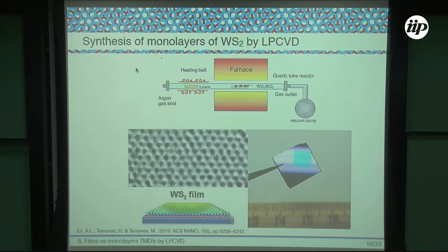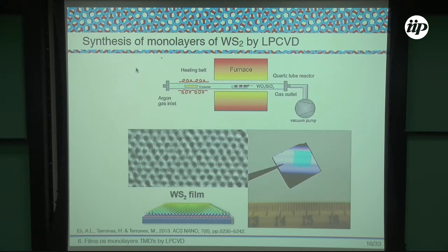This is another type of synthesis — how to synthesize films of TMDs. For some applications, it is better to have large areas of TMDs. To grow these samples, you use low-pressure CVD by adding a vacuum pump at the outlet of the quartz tube to decrease the pressure inside. This gives films of nearly 1×1 cm on silicon. So by changing parameters in the synthesis setup, you can go from single crystal to polycrystal to films, or grow in-plane or out-of-plane heterostructures.